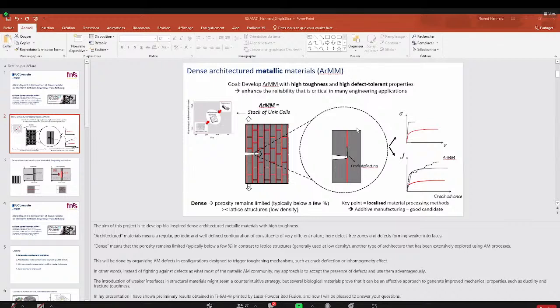Yeah, so in this case, we use Ti6Al4V, so the classical composition. But actually, at least for this strategy, in my talk, I talk about different strategies that could be used to generate interfaces. But if we use defects, such as generated by the Keyhole mechanism, in this case, we use titanium alloys, but this could potentially be applied to multiple types of materials. And that's also one of the interesting points about this strategy, it's more focused, for example, here on a printing strategy than really optimizing the composition of the material.